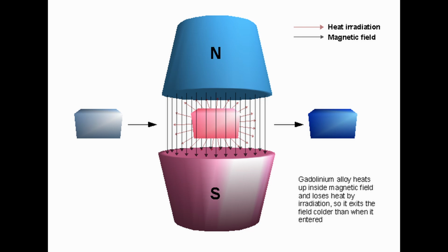Okay. Now, I remember the sources mentioning something about first-order and second-order phase transitions. Is there a practical difference between those for magnetic refrigeration? There is. A first-order transition happens abruptly. The magnetization of the material changes suddenly when you reach that temperature, and it usually involves what we call latent heat, kind of like the energy needed to melt ice. A second-order transition is more gradual, and there's no latent heat involved. So gadolinium, for example, has a second-order transition, which means it behaves pretty predictably and doesn't have much hysteresis. That means it responds smoothly to changes in the magnetic field.